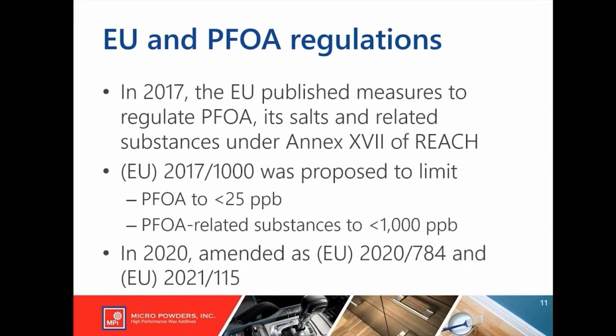So the European Union was the first to look at PFOA and regulate PFOA in the industrial world. This started in 2017, where they proposed to regulate not only PFOA, but salts of PFOA and related small fluorine molecule substances under Annex 17 of REACH. And the first proposal, 2017/1000, made the proposal to limit PFOA content to less than 25 parts per billion and PFOA-related substances to less than 1,000 parts per billion. And then later, the regulations were amended slightly, but basically the driving point was still the same. 25 parts per billion is what you need to achieve to comply.